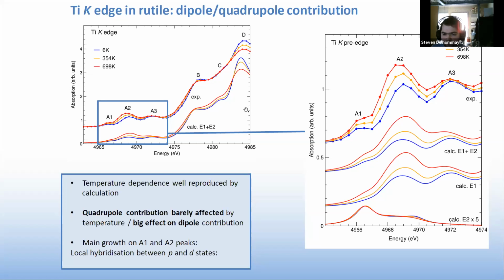So once again, we can start by making some simple observations. We can see that the temperature dependence of the spectra is quite well reproduced. And this is even truer, I would say, when we know that using our theoretical framework, when we calculate the spectra just taking into account thermal expansion, those three spectra are in fact superimposed on each other. There is no change whatsoever. So it's really refreshing to see that we can indeed show such temperature dependency. Oh, sorry, I'm spoiling you.